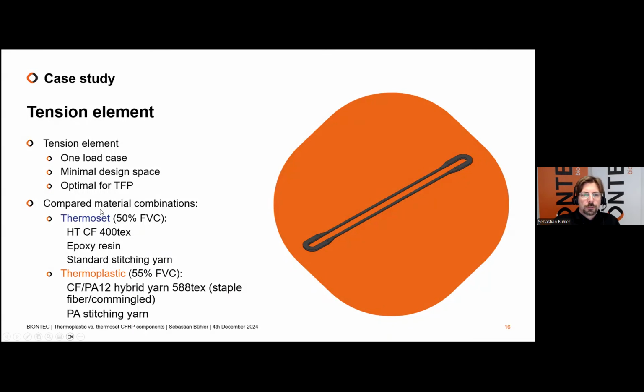For the thermoset setup, we used a high tenacity fiber with 400 tex, a standard epoxy resin, and standard stitching yarn. And for the thermoplastic route, we also chose a high tenacity carbon fiber from the supplier, with a PA12, the polyamide 12 hybrid yarn, with 588 tex. Unfortunately, it was only available as stapled fiber, but later on we will see how this influences the behavior of the part.